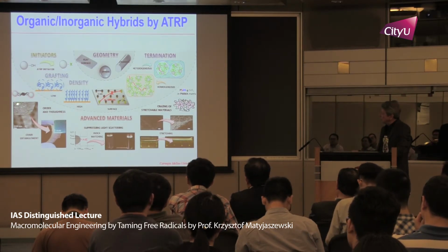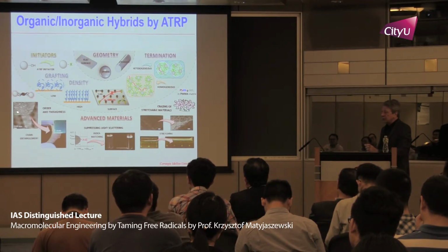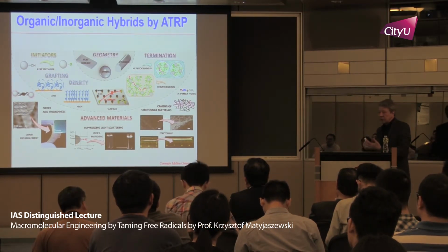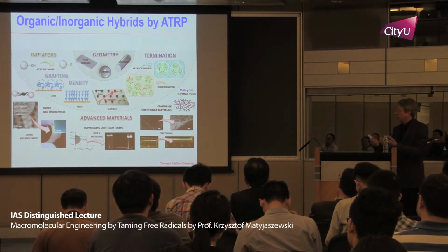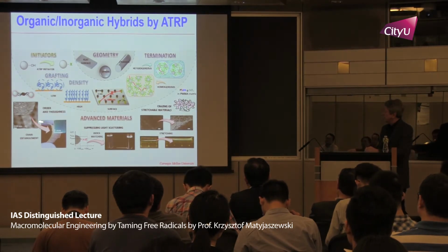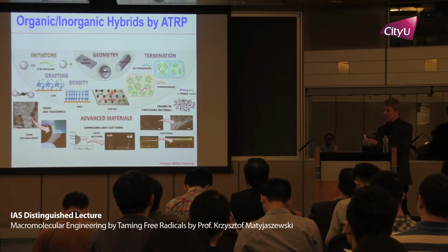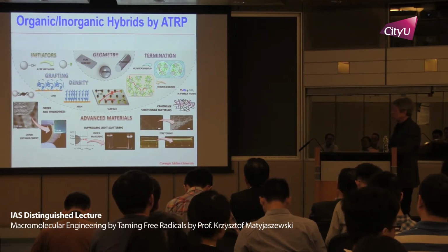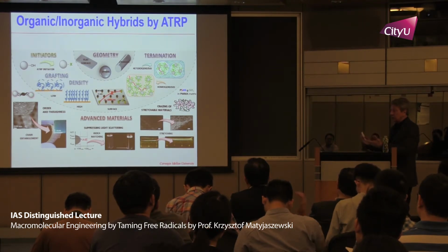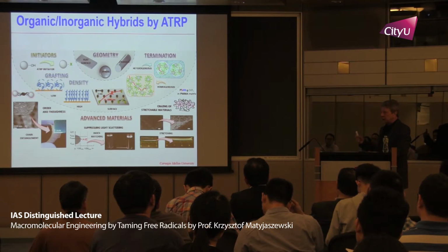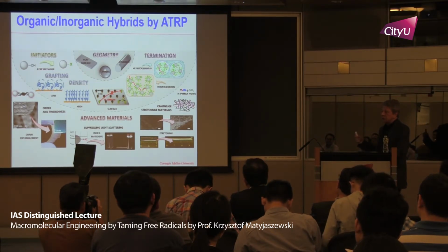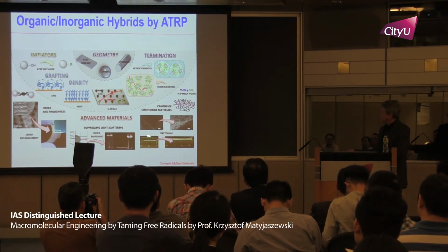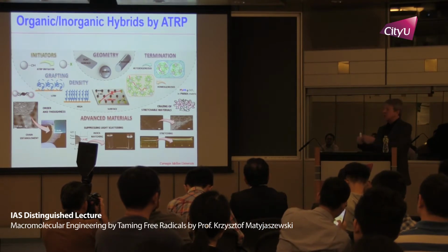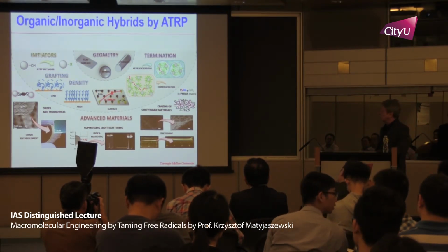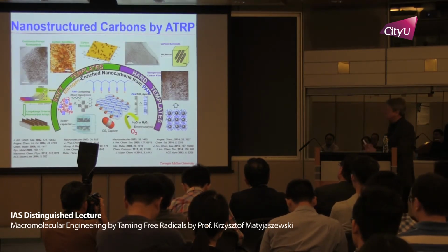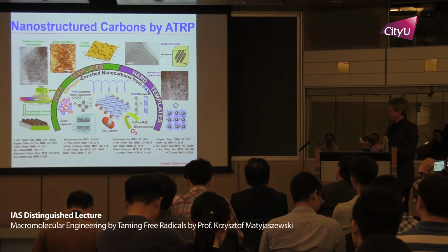So this is one example of a photonic crystal-like material. Silica of 200 nanometers, grafted with polymer. Normally colloidal crystals are very brittle. There is no cohesion force. But here, because you have polymer chains grafted, you can really stretch them, you can bend them, you can also look at what happens under mechanical stress with the change of color. So the classical Bragg diffraction depends on the distance and difference in refractive index. You can load sometimes as much glass as 78% or 75%. So this material is 75% glass, 25% polymer, but you can still stretch it and bend it and it has very good mechanical properties.